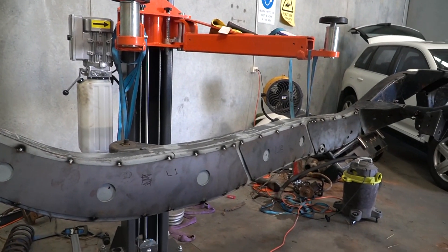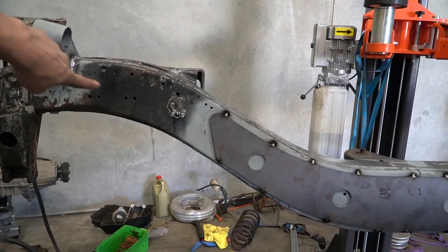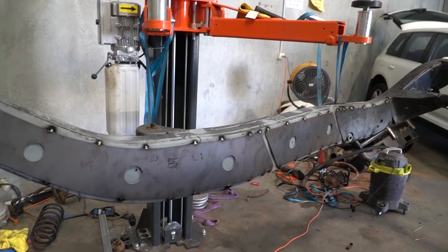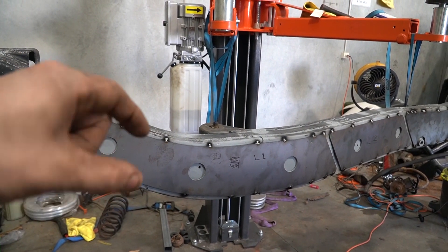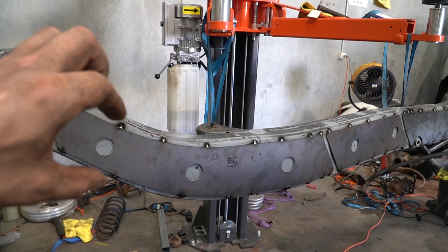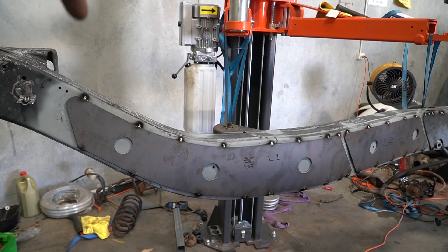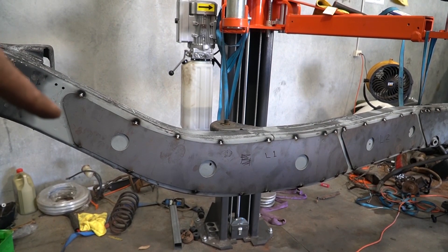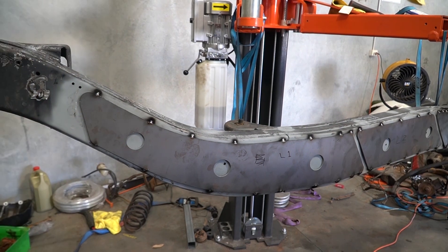I also want to add some wisdom to justify the reasons why I'm not welding all the way around this. Underneath here the frame is full of holes — there's about 10 in this little area alone. So if you fully weld all the stuff around here, you're still going to get dirt and water sandwiched between these two layers regardless. That's why if you weld them all around, all you're going to get is what could be described as a blister, and that's just going to eat its way out from the inside. So if you do these stitch welds along the top and leave a gap, it gives the water a way in but also a way out. What I'll probably end up doing is sealing off the top — do my stitch weld, but between them I'll put some sealant in. I'm going to leave the bottom ones open for the reasons I just mentioned.